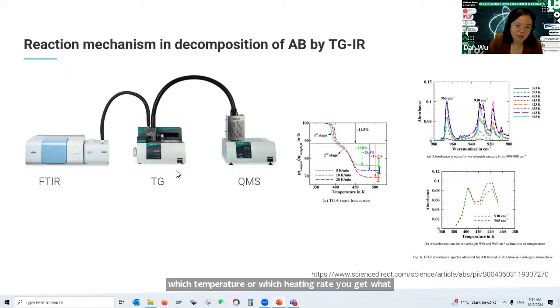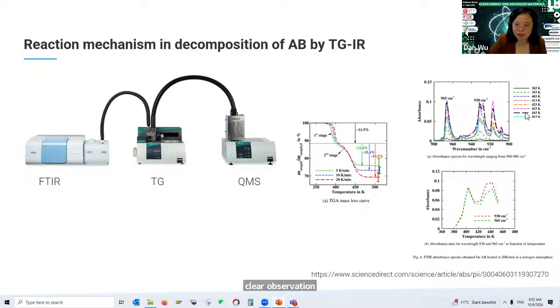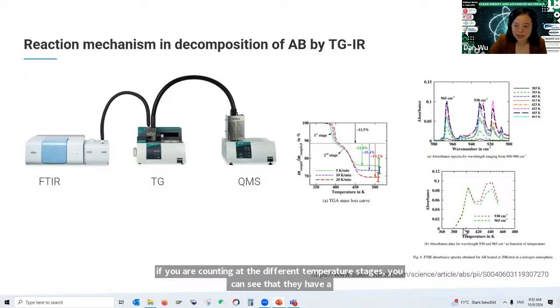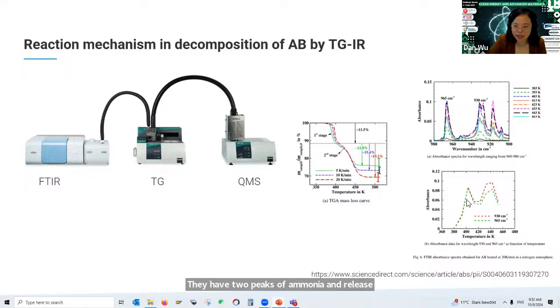from the thermal gravity. And here is simply that they have tried the ammonia borane material with different heating rates. So they are trying 5 Kelvin per minute, 10 Kelvin per minute, and 20 Kelvin per minute. And they have proved that with 20 Kelvin per minute, which is a very fast heating up speed, you can get the most effective release of the ammonia, and also you can have a very clear observation of the ammonia peak at the different temperature. And also here, if you are counting at the different temperature stages, you can see that they have 2 peaks of ammonia release at 400 Kelvin and 450 Kelvin respectively.